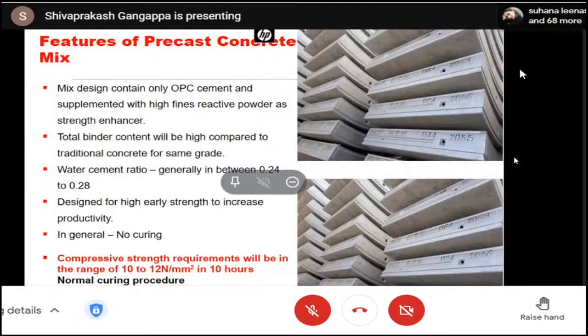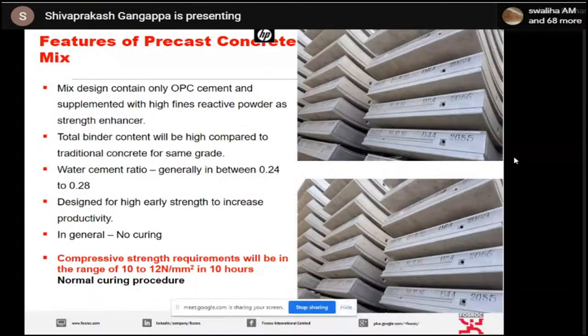Now, when we go to the features of this particular mix design, when it comes to the precast industry, first of all, in most high performance precast concrete the water cement ratio is going to be pretty low. The operating water cement ratio could be between 0.24 and 0.28. Second, high early strength is one more criterion, where people may look for 10 Newton per millimeter square at 10 hours, or 12 Newton per millimeter square at 12 hours. This is the normal trend we come across.